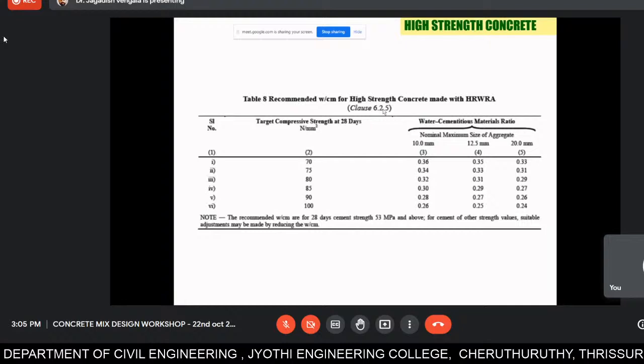And recommended water cement ratio, water to cementitious materials for high range water reducing admixtures. You can see here how much water to cementitious materials you can use for 100 MPa strength. If it is 20 mm down, you can go for 0.24 with high range water reducing admixture. These are some of the guidelines they have given. In mix design, always these are guidelines. It is not that you have to exactly follow. As long as you achieve your workability, achieve your strength, you can follow.